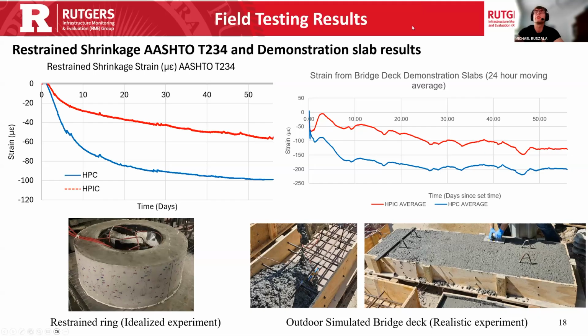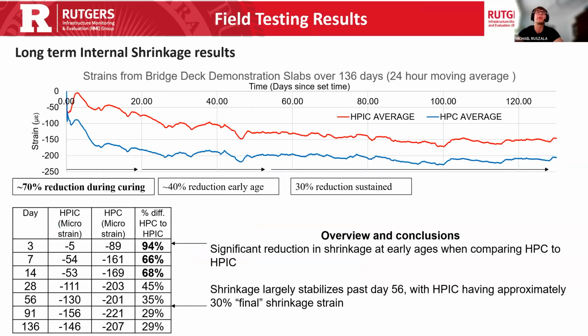sorry, a highly restrained bridge deck reduces the degree of cracking and the forces that develop, specifically at early ages, which I'll go over in the next slide. So you can see that over time, the main benefit is at early ages, which is what we want. We want the concrete to be able to cure properly, gain strength without these strains developing. And we can see that as time goes on, there is a benefit that's maintained, but they kind of converge and stabilize at around 30% past the curing window.